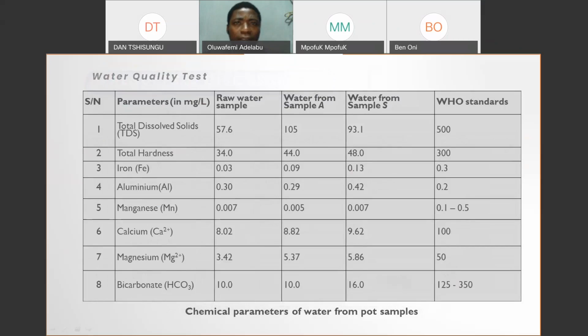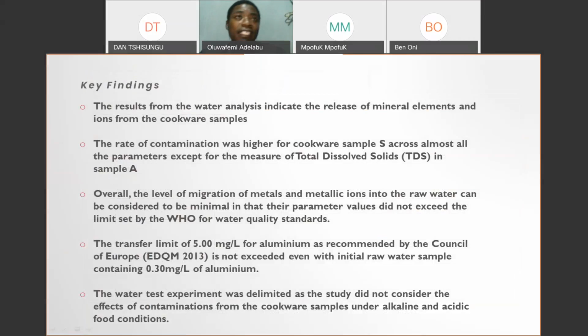And then for the chemical parameters, we tested for total dissolved solids, total hardness, and the presence of iron, aluminum, manganese, calcium, magnesium, and bicarbonates. These are key findings. The result from the water analysis indicates the release of mineral elements and ions from the cookware samples. However, the rate of contamination was noted to be higher for cookware sample S, and cookware sample S was prepared with the additives, whereas cookware sample A was prepared without the additives.